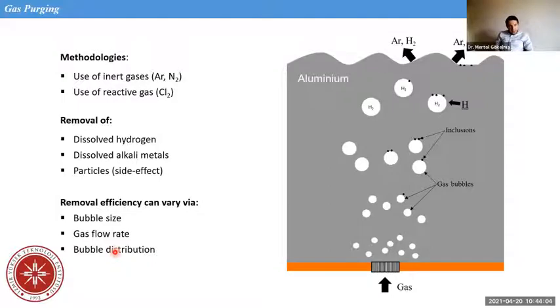The last refining method is gas purging. We do it either with an inert gas, argon or nitrogen, or use a reactive gas like chlorine gas. With the inert gas, we remove the dissolved hydrogen. With reactive gas, we remove alkali metals such as sodium, and sodium attacks chlorine gas and forms sodium chloride, which joins the dross and is removed. And as a side effect, we have particle removal, as in flotation and mineral processing.